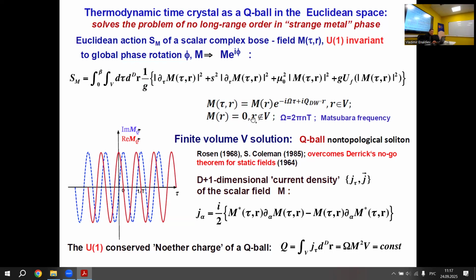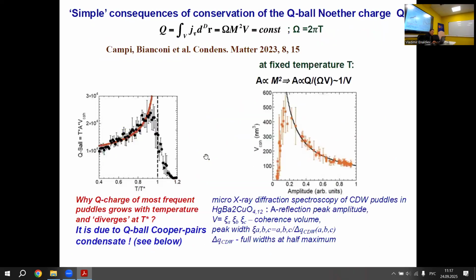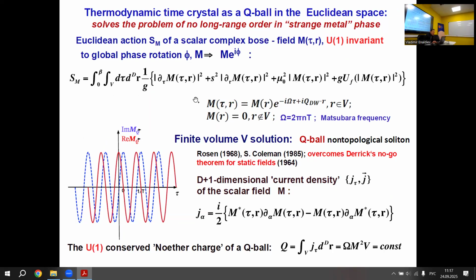So it means that when coordinate r does not belong to the volume of the QBall, there is no deformation, it is zero. And this finite volume solution exists due to this trick with the Matsubara time-dependent phase of the deformation field. Then one should introduce the so-called d plus one dimensional current density, which has the usual current density and a time component of current according to this formula, which is more or less trivial.